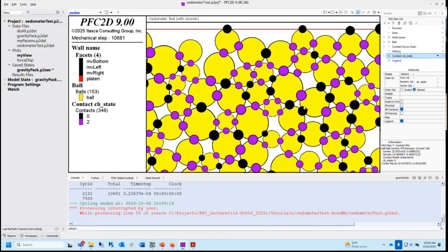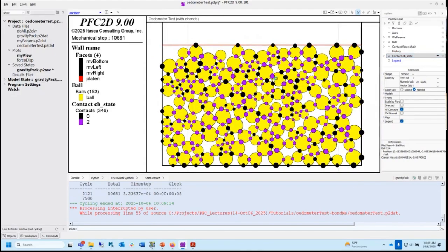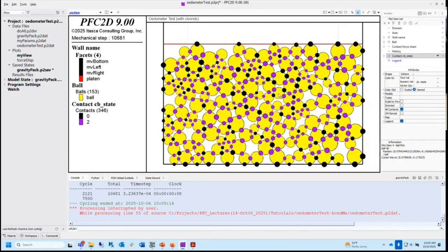You're starting to see this microstructure is very sophisticated, and this is the simplest possible model. You have a system that's packed, but you have a lot of guys that are close to each other. And now you're going to put in cement, which I'm going to say bond. And the question is, does the bonding fill the gaps or not? So by default, it doesn't fill the gaps. It just gets put where they're touching. But now you've got this system with these small gaps. So when you start compressing it, it's going to start getting stiffer because it's going to make these new things. So effectively, this initial system that we created had a whole bunch of gaps in it. And those gaps are beginning to close.